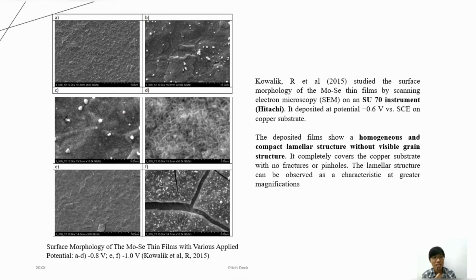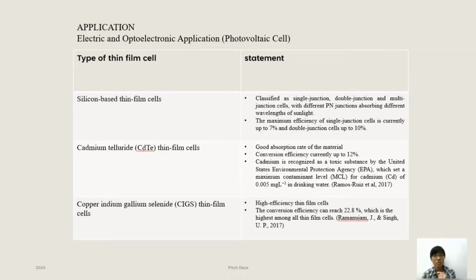Kowalik studied the surface morphology of a molybdenum chalcogenide thin film by scanning electron microscopy, using an SU-70 instrument. It was deposited at a potential of negative 0.6 volts on copper substrates. It shows a homogeneous and compact lamellar structure without any visible grain structure, and it completely covers the copper substrate without any fractures or pinholes. One of the applications of thin films is in electrical and optoelectronic applications.